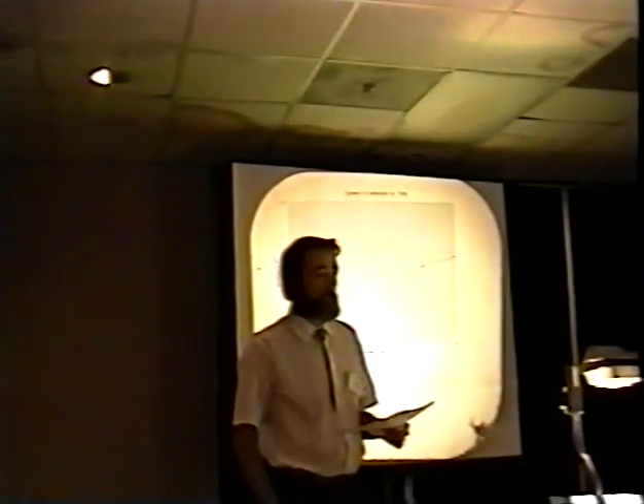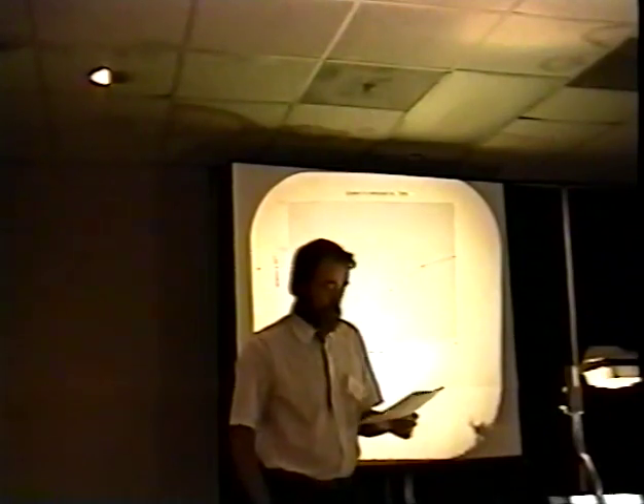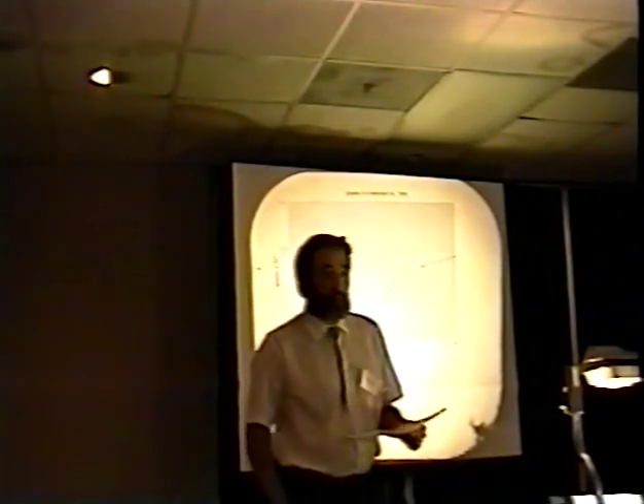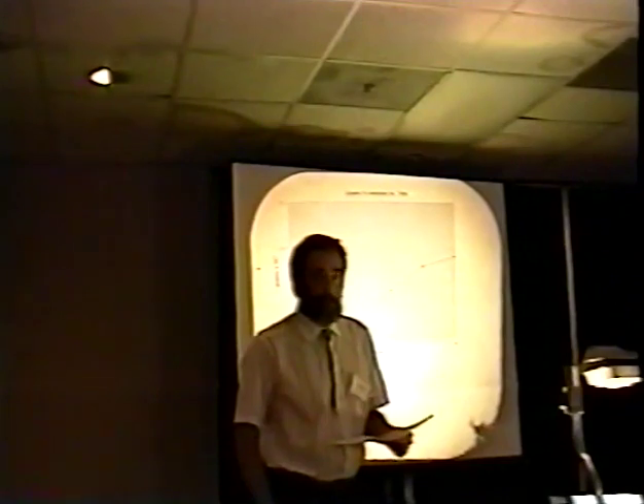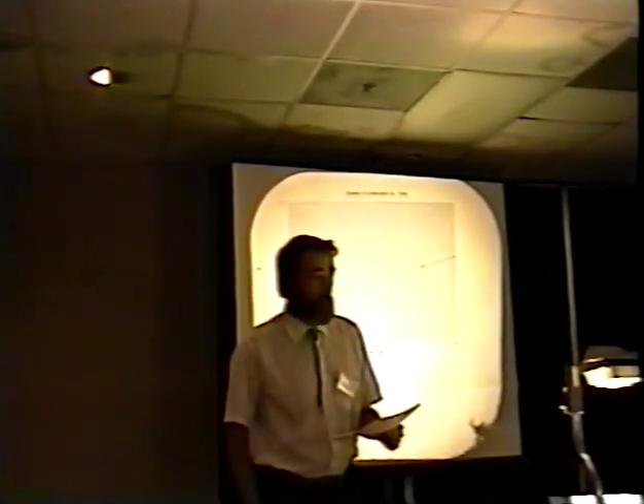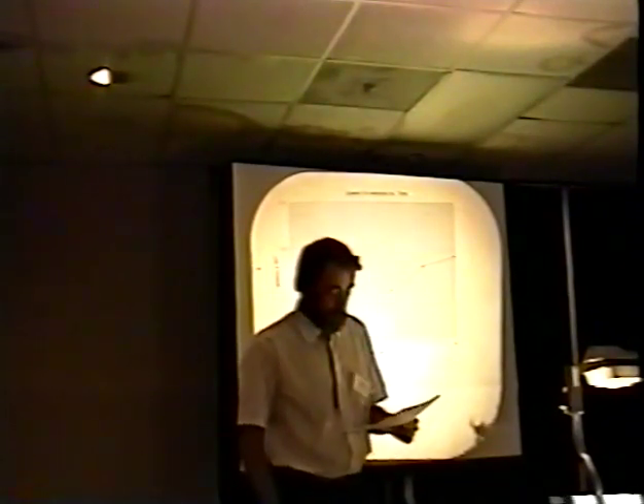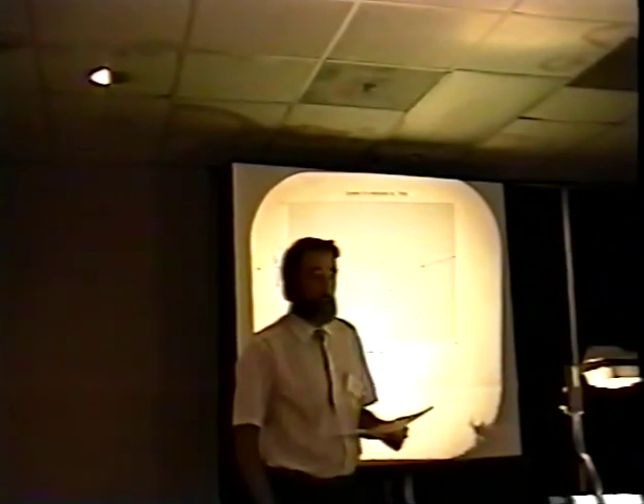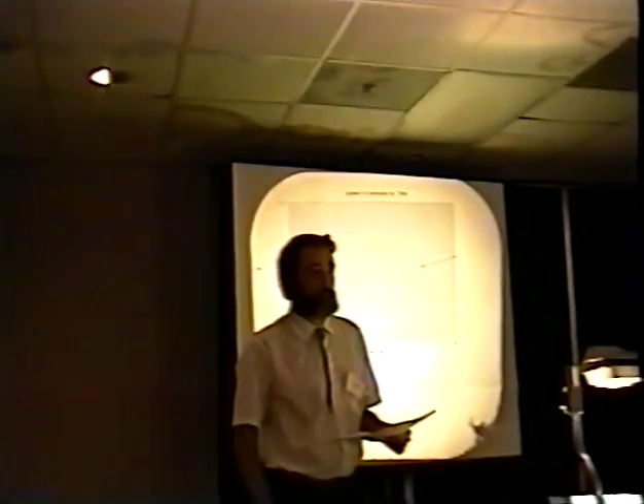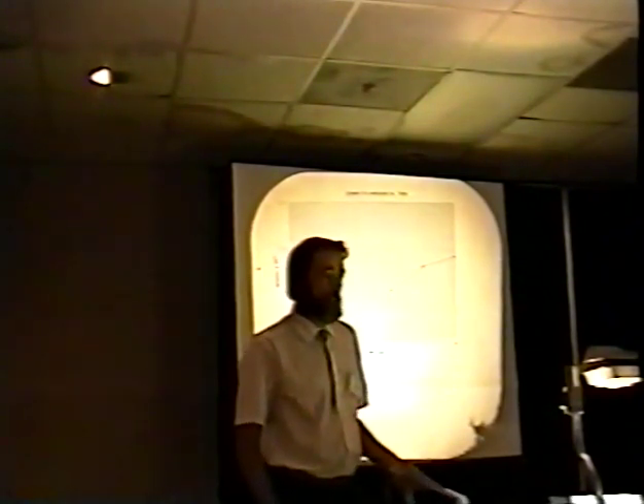Now here's the kicker, and somewhat confusing based on what Dr. Bachrach has found and what Ishii has reported. When we first tried this experiment, we went to the chemical supply house and asked for carbon. They gave us this Mallinckrodt charcoal, which was 100% carbonized material, supposedly no heavy metals, no iron, although the percentages weren't available. They didn't have ppms available to us. But when we first used the very fine powder, the charcoal powder, we found that we could not get any iron formation in the arc, which is why we went to activated charcoal, which we could get from a pet supply store. Can you show the composition of your carbon?